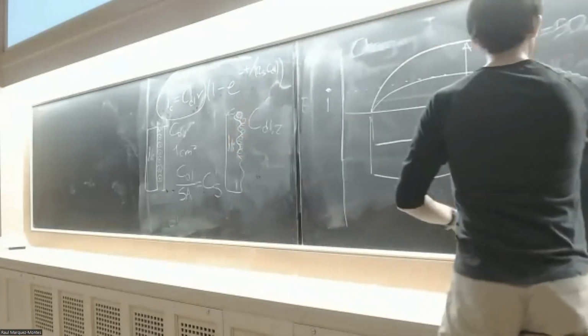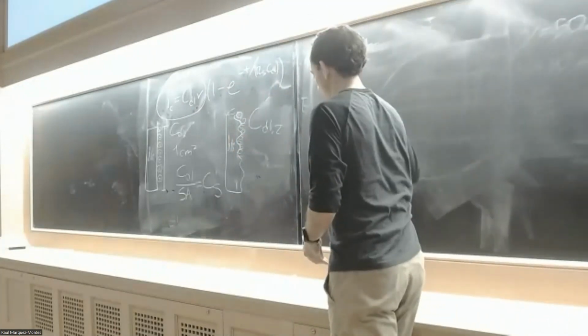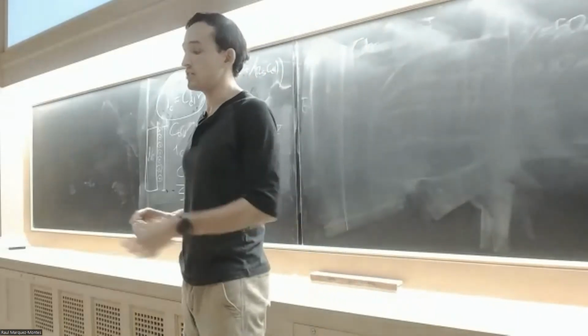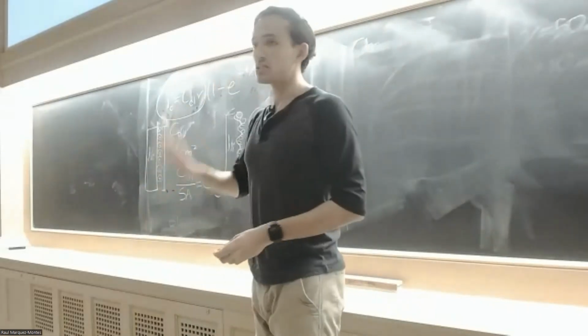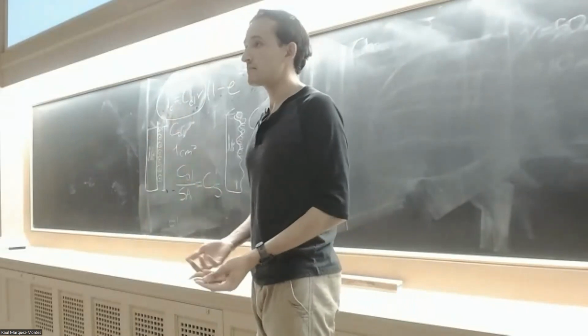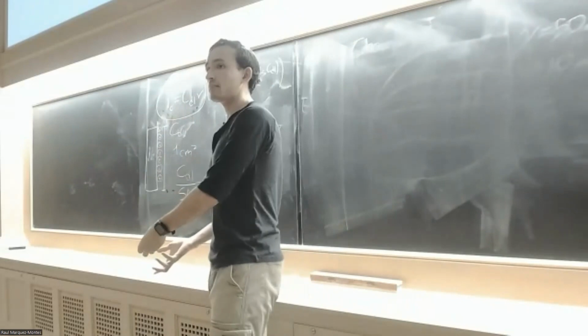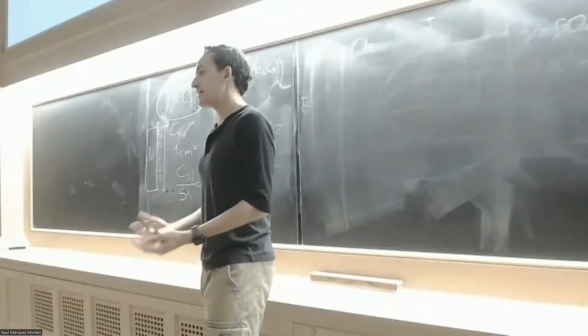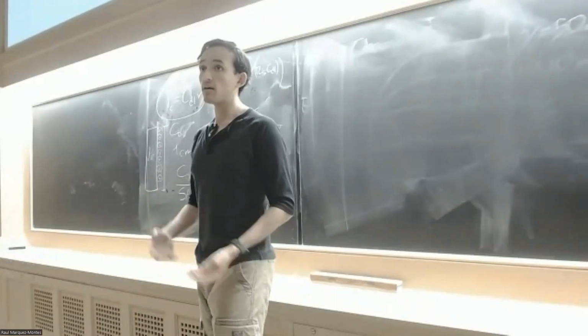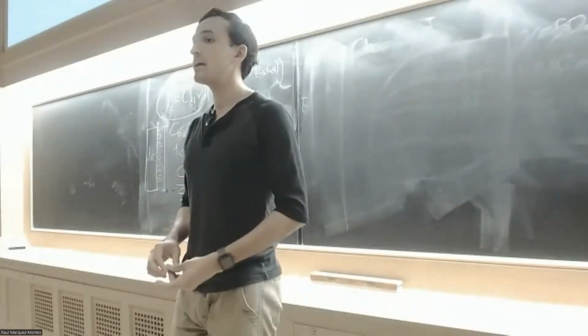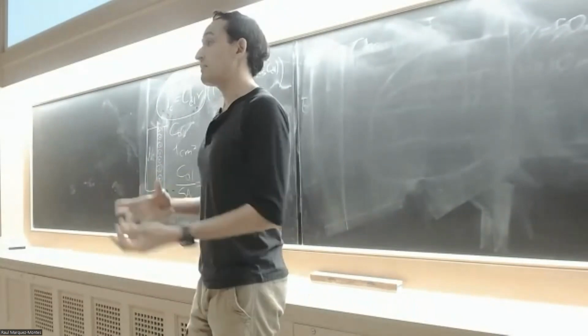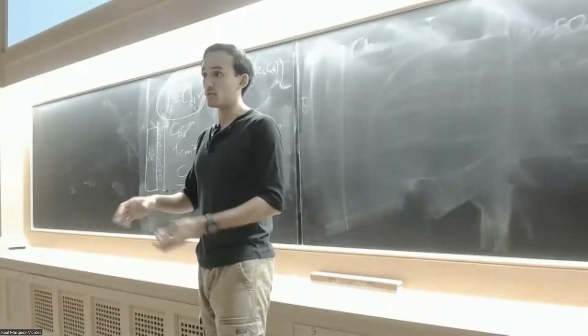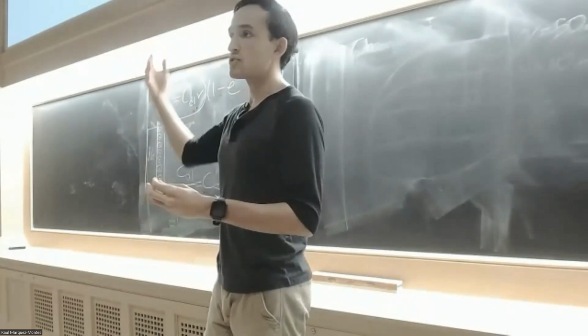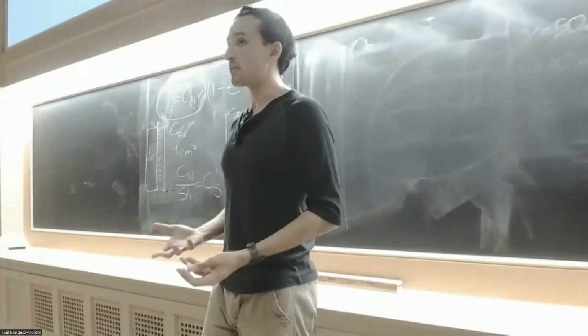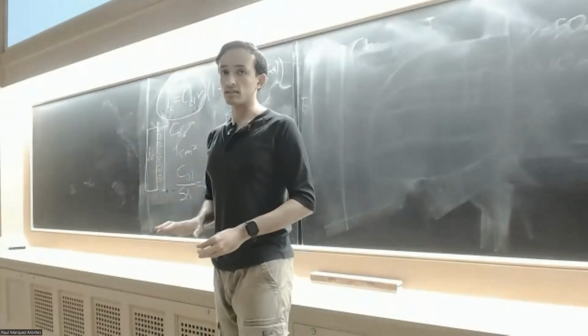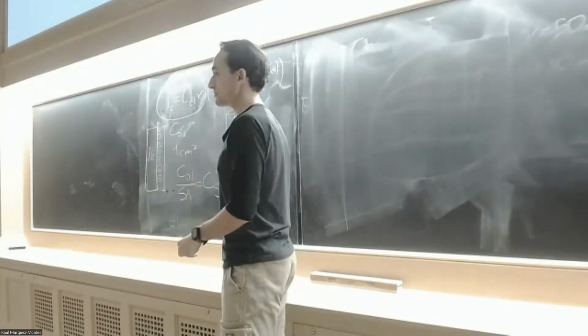Just before doing that, I will explain really quick some important considerations that you need to take into account. The first one: the material must be conductive. If your material is not conductive, you're not able to apply negative bias and drag the charges. Only metals and some metal oxides are conductive. For semiconductors, it depends on whether you're sure the material is conductive when you apply a certain potential, or when you shine light, those kinds of properties. But you need to make sure the material is conductive. If it's not, this measurement is not reliable.